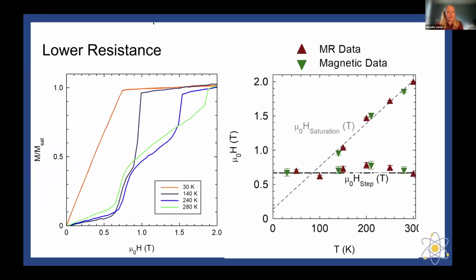So if we were to take a look at the lower resistance state and compare it to the magnetization, what we see for the lower resistance state is that it's the area between 0.75 Tesla and where we see that saturation peak. And this graph to the right actually shows we have this persistent magnetoresistance step at 0.75 Tesla, which is related to the dark black curve. And then right where it saturates, where we have that little increase again in the magnetoresistance, that is where we actually have the saturation field. And you can see that it behaves pretty similar to each other.